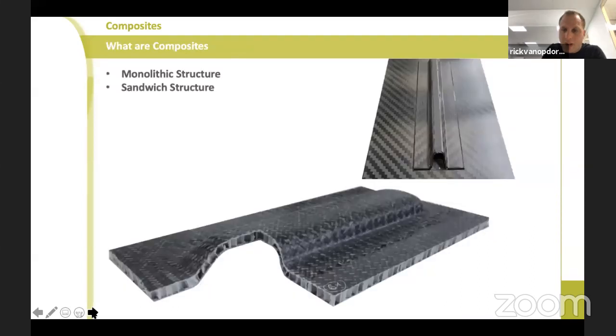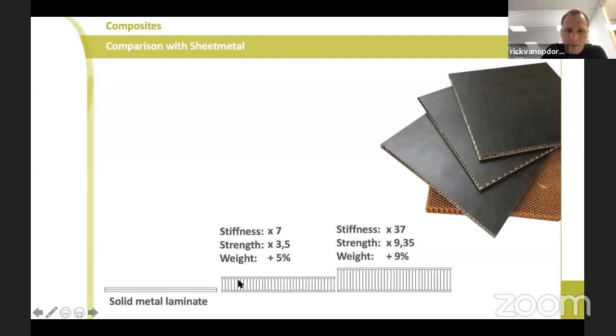So you have two kinds of structures. The monolithic structure is only a solid laminate, which you see in the top right corner. And on the left, you see a sandwich structure. The name sandwich already mentions it: there's something in between. I will mention the sandwich structure a few slides further. What you see here is a solid laminate, and adding something in between, in this case honeycomb, you see that the stiffness goes up by 37 times, and the weight barely goes up. So you make a product very stiff and very strong, and the weight almost doesn't go up.